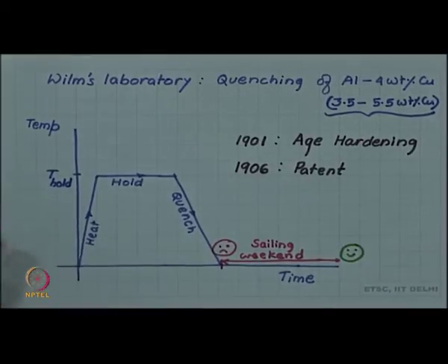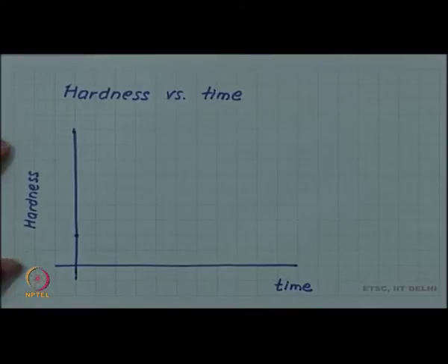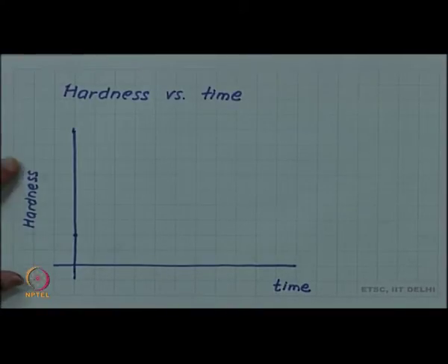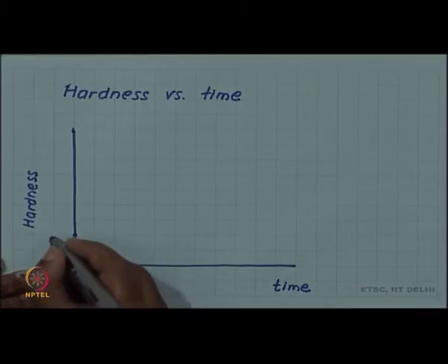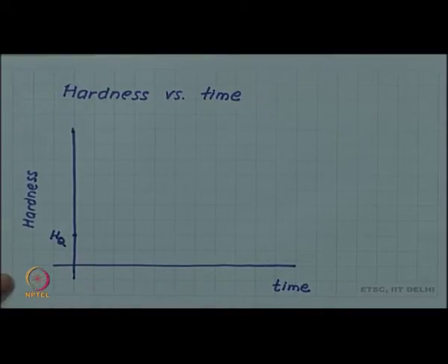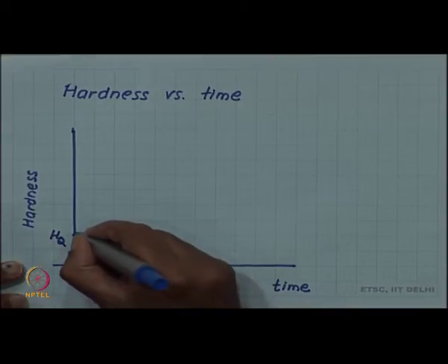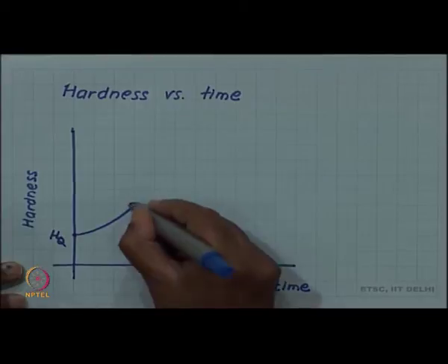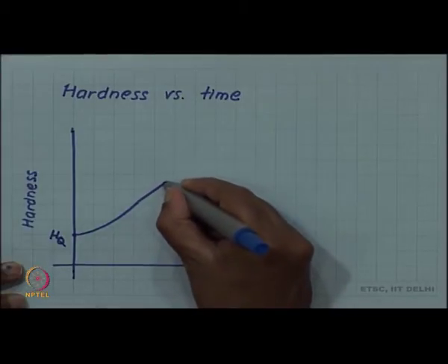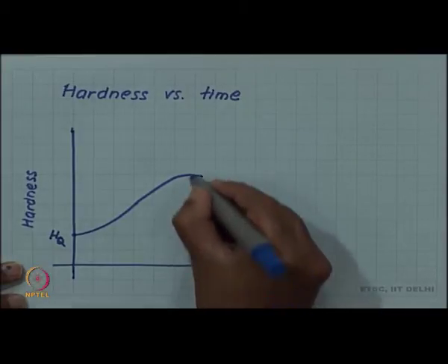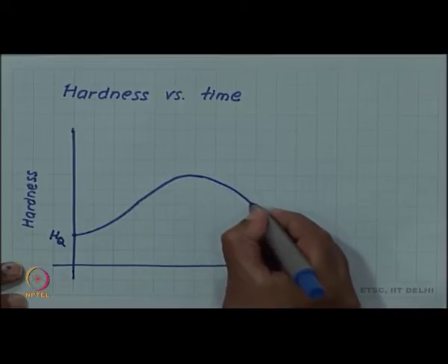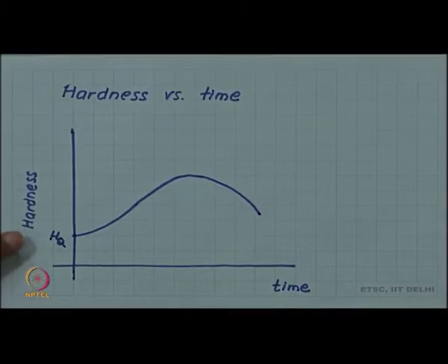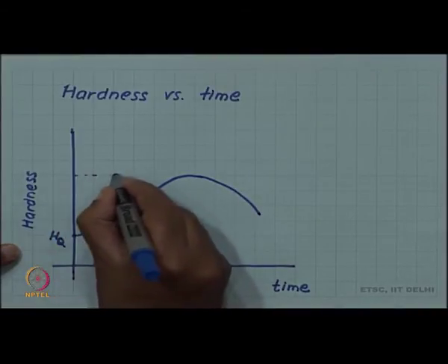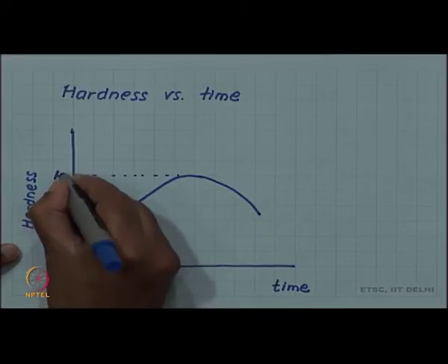So, let us look at what he found on aging, or how does the hardness change as a function of time. So, after quenching, there is a hardness value, and let us call that HQ, hardness in the quenched state. And then as time passes, the hardness starts increasing and starts going up. But then at some point, it reaches a peak and then decreases. Let us call this hardness the peak hardness.